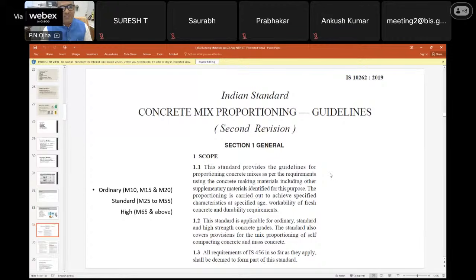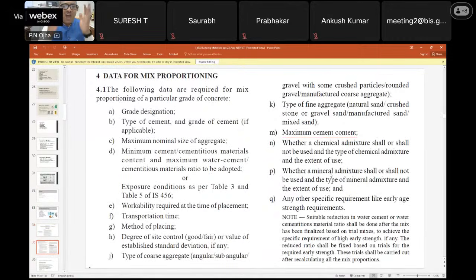Okay, and you must be aware of what is self-compacting concrete, what is mass concrete. So there are some differences. You must be aware about it. And this is the first page, and you can see which data should be available for going ahead for concrete mix design, from A to Q. All these data should be available: exposure condition, maximum cement content, method of placing, transportation time, what is the maximum size of aggregate, which type of cement is to be used, what is the grade of concrete, what is the degree of site control, type of coarse aggregate. So all these data should be available. Taking them together, we design the mix proportion.